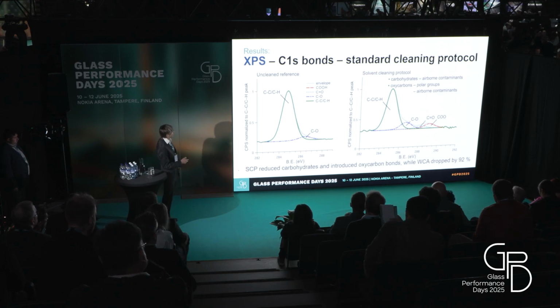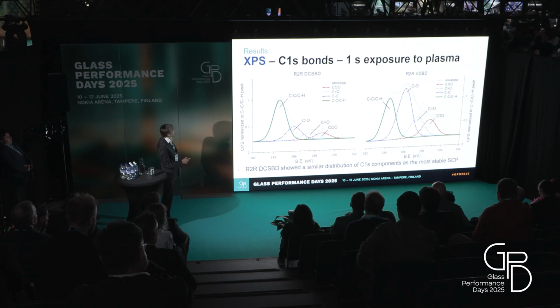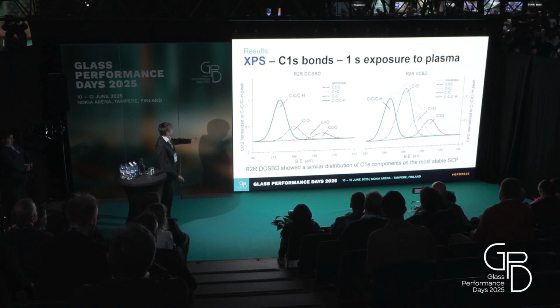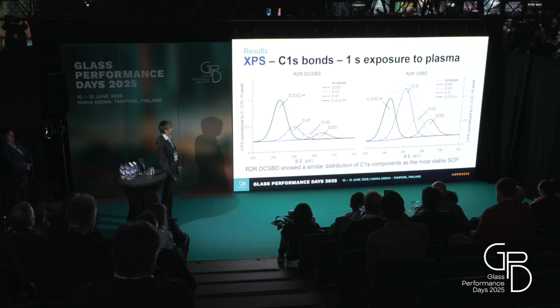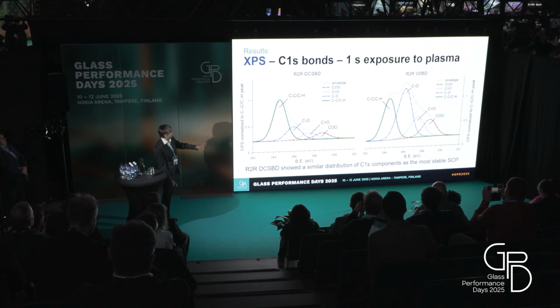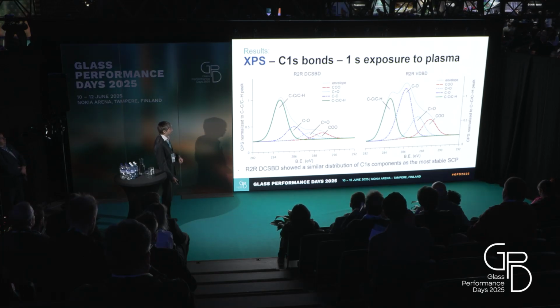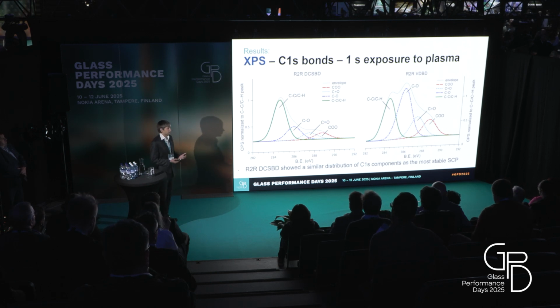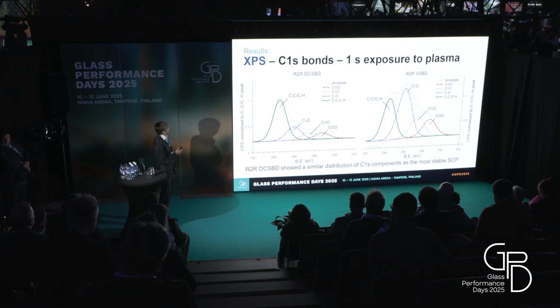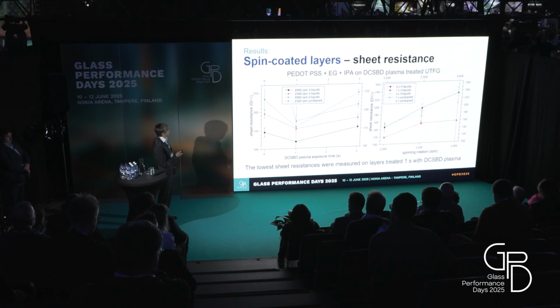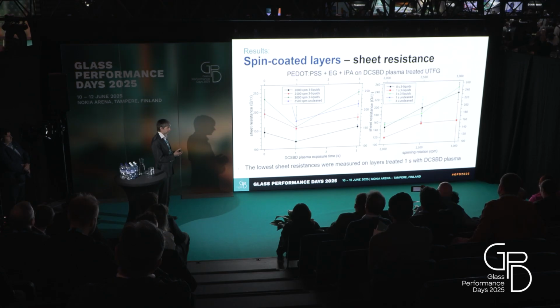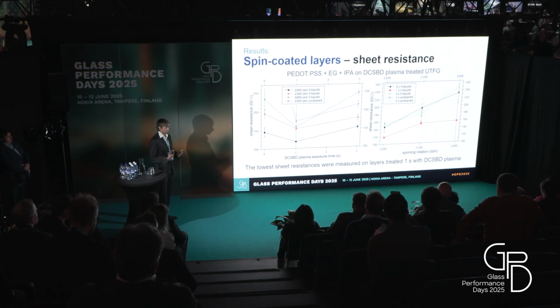And if we now look at the plasma treated samples, the DCSBD plasma treated flexible glass surface looks very, very similar, while the composition on the surface with VDBD changed. So this is a higher and unstable change, which is not similar to the solvent cleaning protocol. Therefore, we expect that DCSBD is more regular, and its effect is comparable with the solvent cleaning protocol. And we applied it for the plasma treatment before the coatings.